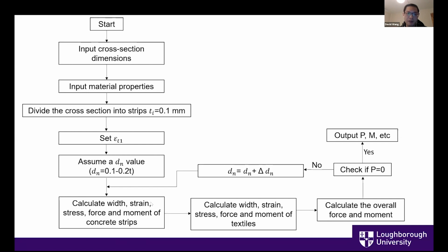In our study, the width of each strip is 0.1 millimeter. Because in our study, all the failures of the specimens are caused by the failure of the textile, we will set the bottom layer of textile, the tensile strain of the last layer of the textile, as the dominating factor for this analysis.